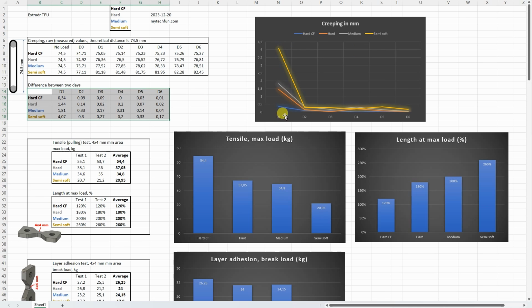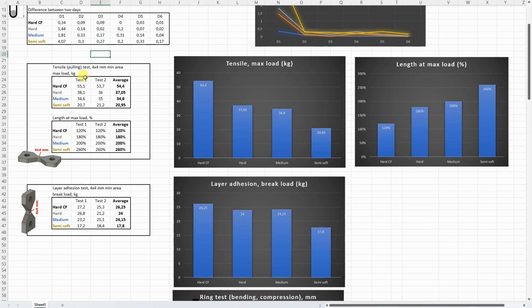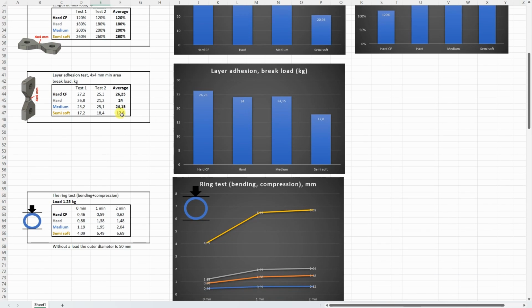And here you can see that after day 1 we still have some creeping. The minimal is on the carbon fiber version. But after day 2, basically that creeping stopped with every material. On a tensile or pulling test, we can see that here the best was the hard carbon fiber version, but with the smallest elasticity. On the layer adhesion test, these are all acceptable values for the TPU materials, and it was very good to see that we have some elasticity before the break with each filament here.